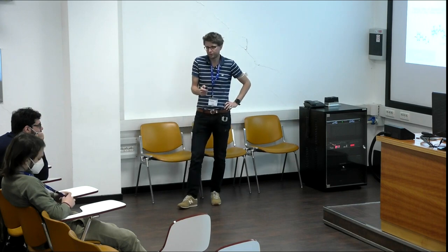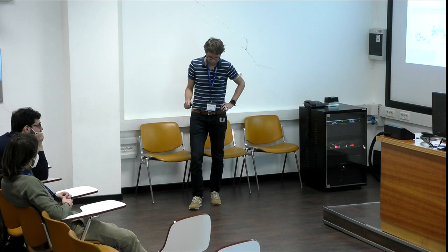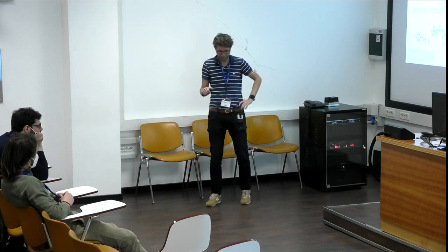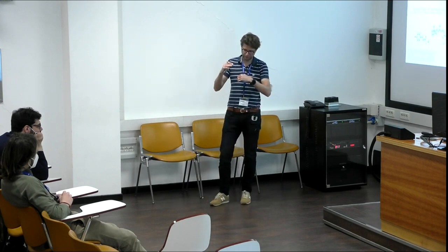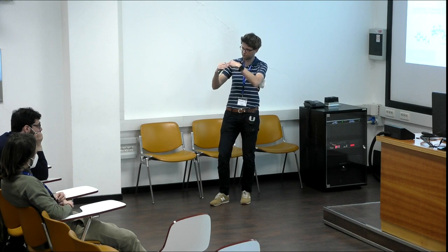In the literature, there is a lot on using TD-DFT for magnons. And usually the issue is not the interaction, so the exchange-correlation kernel of TD-DFT is already pretty good. The reason is that you have a magnetic system and you have an exchange splitting between the spin-up and spin-down bands. So to get a magnon, you need a kernel which is able to close that.